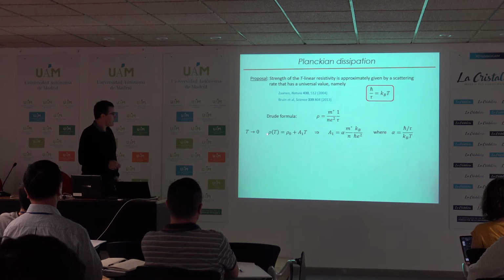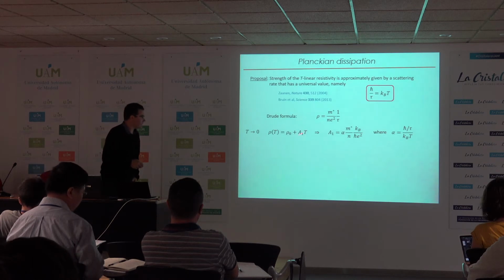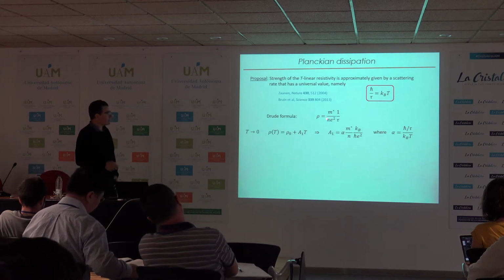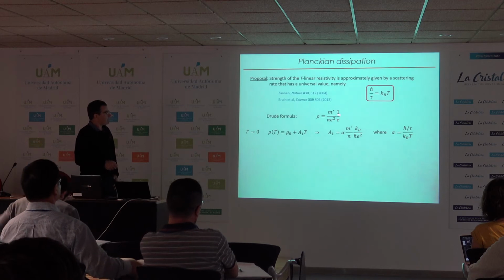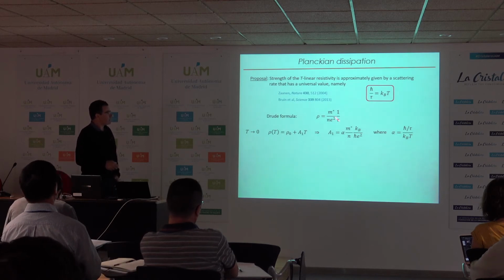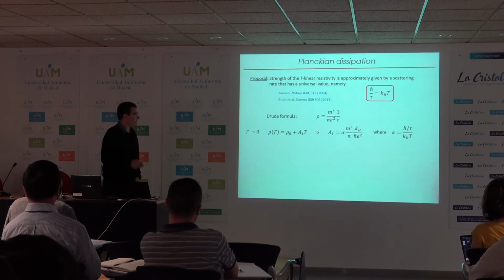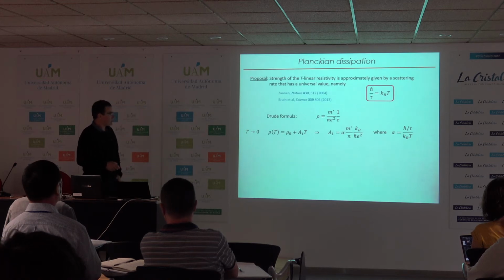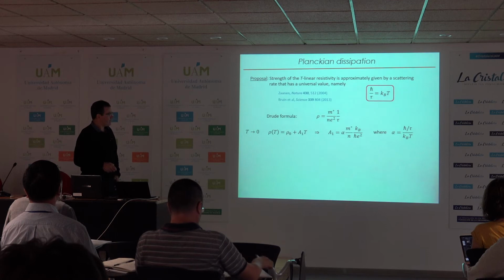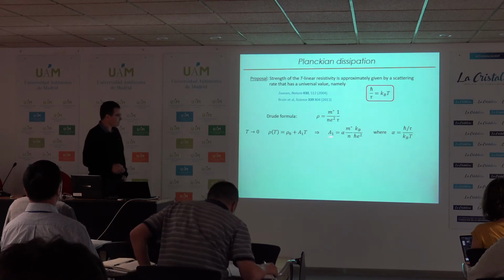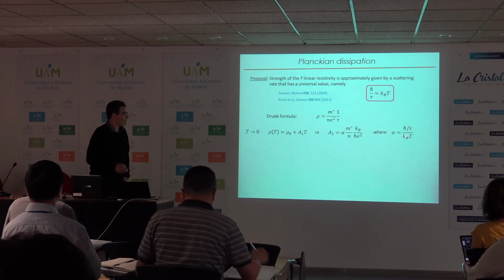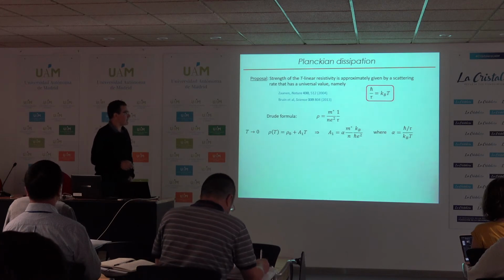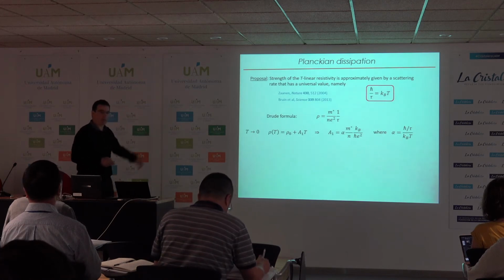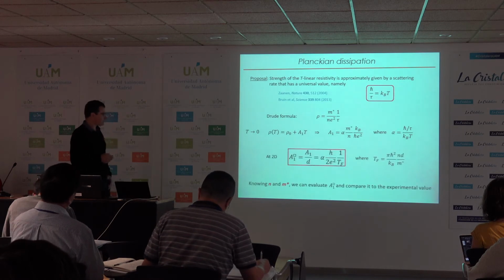deduce some parameters. If you have a T-linear resistivity, you can write the resistivity as ρ0 plus A1 coefficient times T. And so you replace the scattering rate by kBT over ħ. You basically arrive at a formula where the A1 coefficient can be written like this. With alpha being the ratio, so alpha equals 1 basically when you have the Planckian dissipation limit.